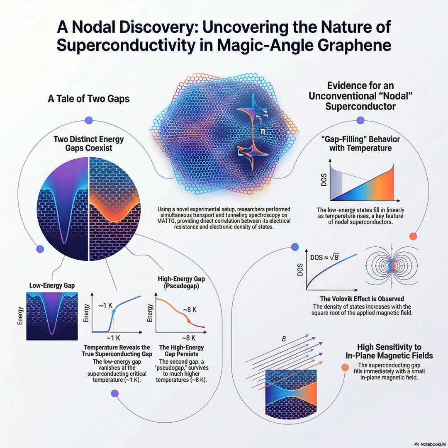It is. They stacked 2 layers of MATTG, a top one and a bottom one, and they sandwiched a thin insulating wall of hexagonal boron nitride, or HBN, right between them. This is the crucial part. So the stack is essentially a vertical tunnel, 2 separate superconducting layers, but they're close enough that electrons can tunnel through that HBN wall. Yes, when you apply a small voltage, that's the bias.